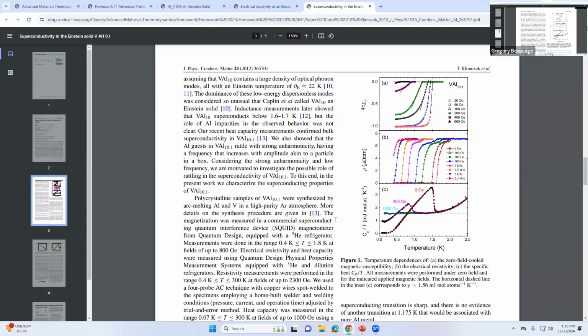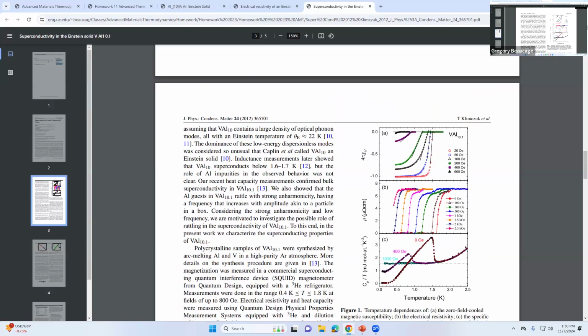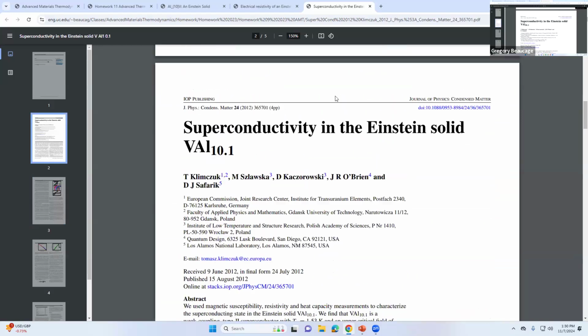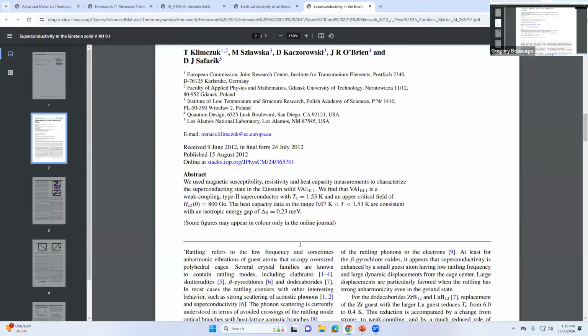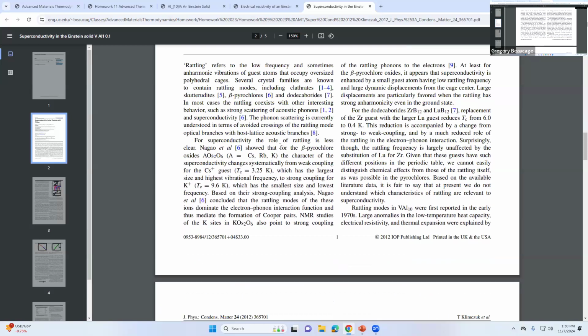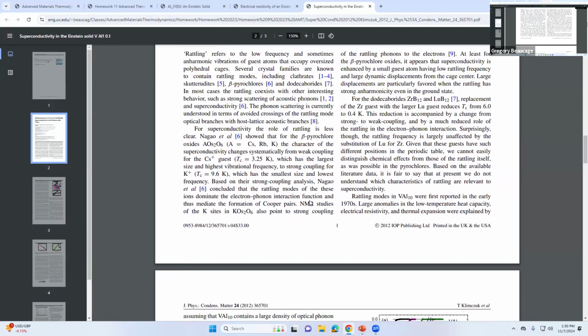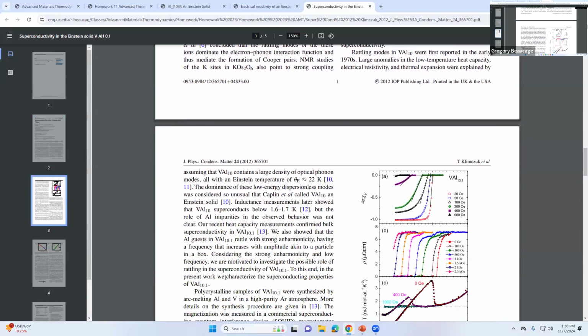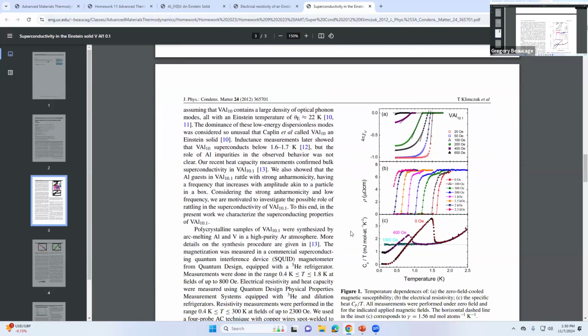But once you have that, he even tells how to do it, and it's pretty easy to make these alloys. It's pretty simple. You just mix it together and let it anneal for 80 hours in an oven at some high temperature. And that's it. Then you have a little puck you can put in the DSC, or you can make a rod to measure the modulus or whatever he does with it. So he makes different size things to get these different measurements.